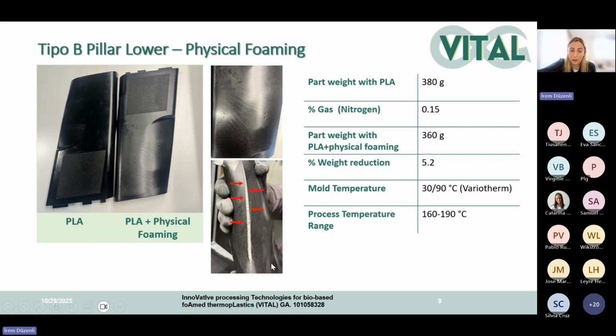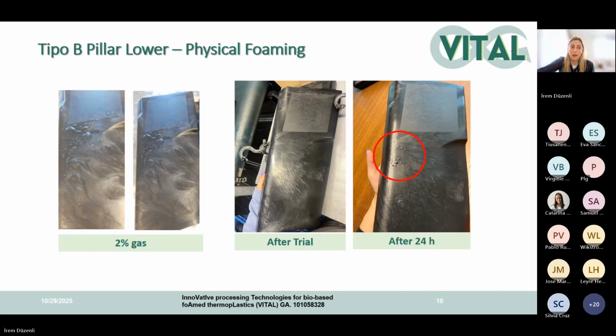And also you can see some bubbles on the cells in the parts. In physical foaming, we use nitrogen gas in the process, and it's a very low amount of gas, like 0.15. And also we achieve weight reduction of almost 5%. And these temperature ranges are quite higher than chemical foaming, because we have no problems with brittleness in these parts with just physical foaming. And you can see some pictures of other trials.